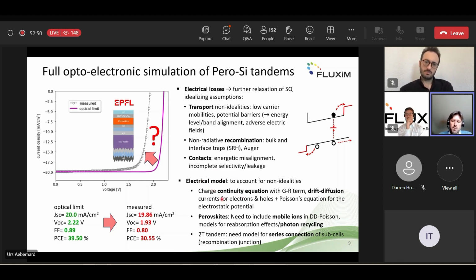The standard electrical model for solar cells is based on the charge continuity equations, including a generation and recombination term, with currents that are described by drift diffusion terms for electrons and holes, and this is coupled to the Poisson equation for the electrostatic potential. Now, in the case of perovskite, we also need to include mobile ions in the drift diffusion Poisson framework. And in perovskite, we also have the situation that we have a highly emissive system, or let's say we are often relatively close to the radiative limit. And in this situation, reabsorption effect and photon recycling can also start to play a role. Now, for two-terminal tandems, as we are considering here, we of course also need a model for the series interconnection of the subcells, meaning the recombination junction.